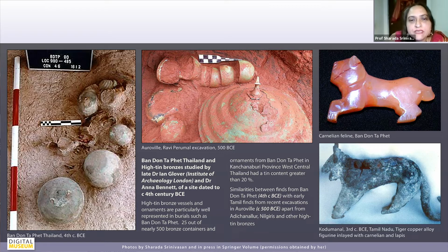Now, there are also these similarities between material from Ban Don Ta Phet, which is a site quite well dated to about the 4th century BCE in Thailand, with some of the early Tamil finds, such as from the excavations in Auroville that I've been talking about, 500 BC, apart from Adichanallur and Nilgiris and so on. And of course, Ban Don Ta Phet had also been worked on a lot in the 70s and 80s, by Bennett, Glover and various other scholars, and also then Vincent Pigott and Elizabeth Moore and various other people. Out of about 500 bronze containers, about 25 of these had a tin content of more than about 20%. And you also find, for instance, this carnelian feline from Ban Don Ta Phet, and from Kodumanal from the 3rd century BCE in Tamil Nadu, you also find this tiger, a copper alloy figurine, inlaid with carnelian and lapis lazuli. So again, these similarities come to mind.